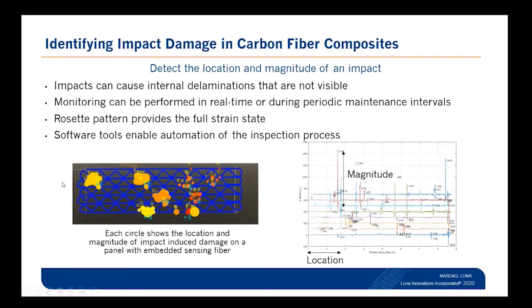and when that panel is damaged, whether it be from an impact or from cracking as a function of fatigue, we'll start to see a strain signal at that location on the fiber, pull out its magnitude, and then we can provide that data to determine if this part should still remain in service, or to try and enable engineers and analysts to come up with what might be happening in this case. One of the other advantages when we lay the fiber out in a pattern like this is we're effectively creating rosettes across the entire part. So that also enables us to evaluate the full strain state of the part.